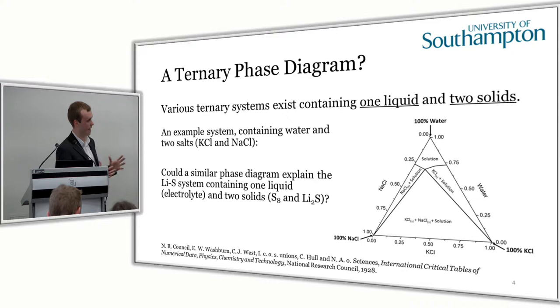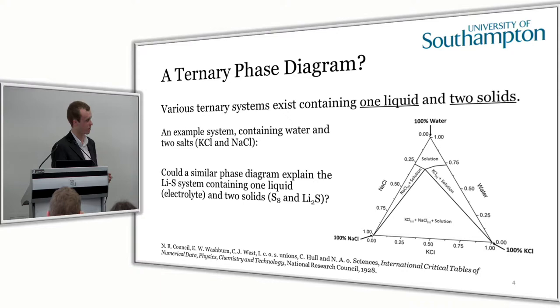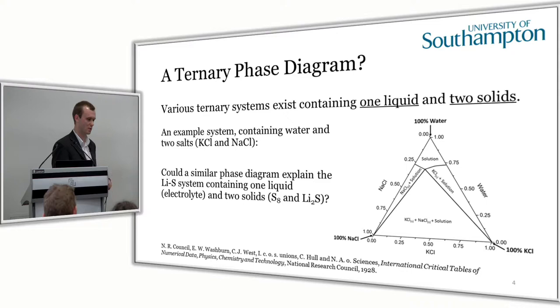At the bottom we have the interesting three-phase region, where we have both solids present — sodium chloride and potassium chloride — and we have the solution. Only at this point is the solution completely saturated with respect to both solids. We thought: could we not use a similar system to help explain the lithium-sulfur battery? We could use our electrolyte as the one liquid, and our two solids being solid sulfur and solid lithium sulfide.